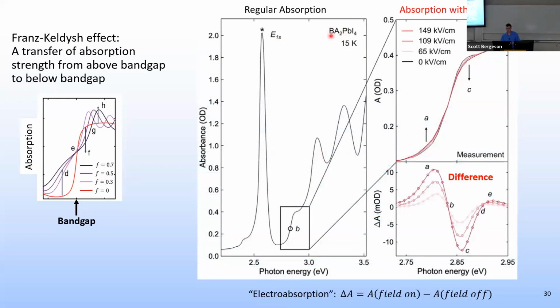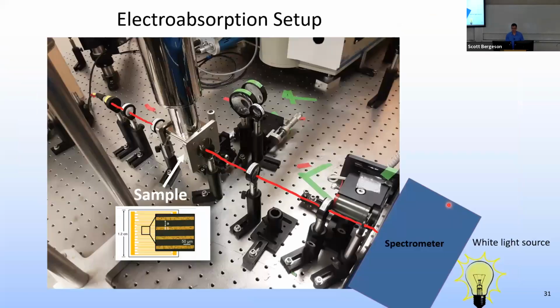So this is now butylammonium lead iodide. Here's the absorption for butylammonium lead iodide, and we were able to identify this right here as being the band gap by looking at the electric field response. And when we turn on electric fields, we get an increase in the absorption here, a decrease in the absorption here. So if you look at the difference, basically right in the middle there is where the band gap is. And this is called electroabsorption, just the difference between the absorption with the electric field on compared to the electric field turned off.